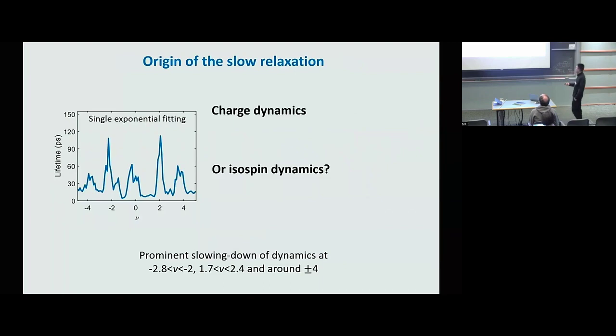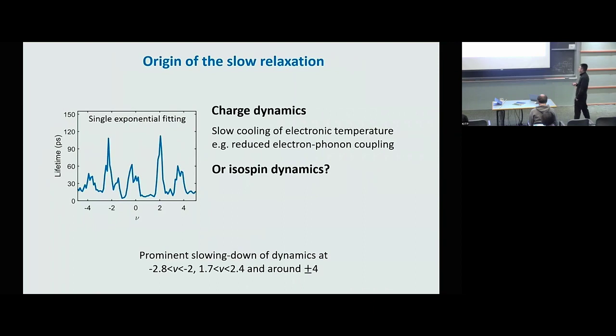Now we know the relaxation dynamics. The most important question we want to ask is, what are these dynamics corresponding to? What's the process giving all these dynamics? In particular, are they coming from charge dynamics or isospin dynamics? This is a very different scenario. If it's coming from charge dynamics, then a slow relaxation means a slow cooling of the electron temperature, which typically comes from reduced electron-phonon coupling, like a phonon bottleneck. But if it's isospin dynamics, then it's more exotic. It tells us that isospin orders are recovering very slowly, and there are some long-lived isospin modes in this region.